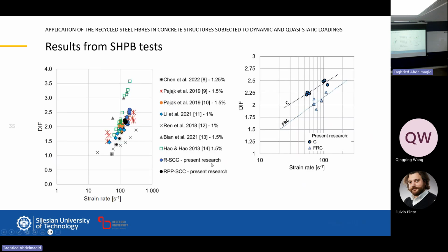And when we compare it generally with concrete and with the other results, this is the strain rate sensitivity of concrete. Generally the fibers decrease it. All types of fibers decrease it. So let's say we have concrete with very high strength, so it is less strain rate sensitive than concrete with lower strength. Here the fiber reinforced concrete is stronger, so it has lower strain rate sensitivity. In the case of recycled steel fibers, we achieve exactly the same results as we get with other fibers. So it is useful in the same way in these applications.